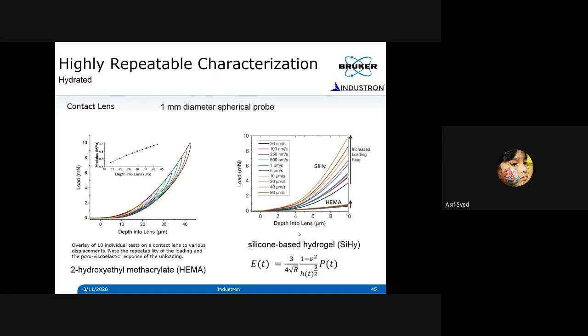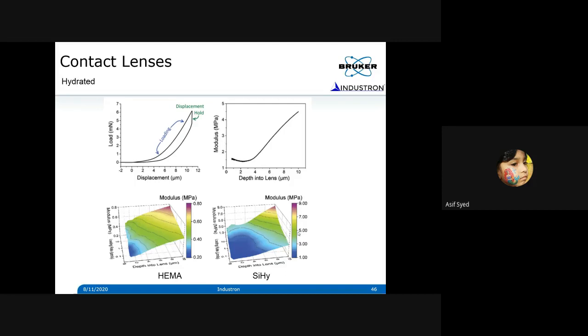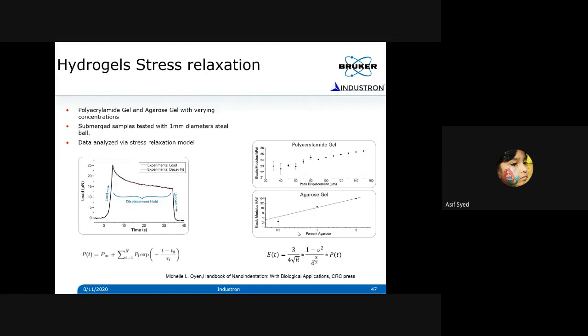Same thing here now with a different loading rate. The silicone-based hydrogel in this particular experiment shows loading rate dependency, whereas HEMA doesn't show much loading rate dependency. It depends upon the formulation of how the contact lenses were made. Okay, now as I mentioned, you can use straight away Hertzian contact, or slightly modified Hertzian contact, and measure the modulus, and you can get a map of it. That's what I'm showing over here between these two different materials. Okay, and you can also do another type of test on this hydrogel contact lens, which is a stress relaxation experiment, where you load the sample.